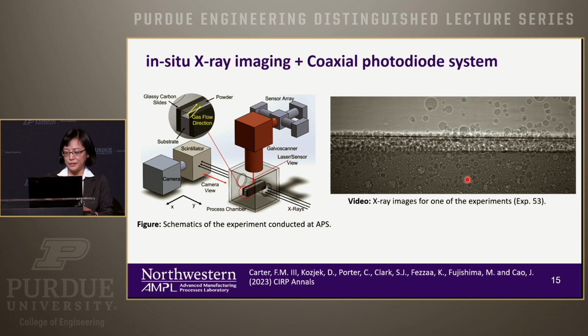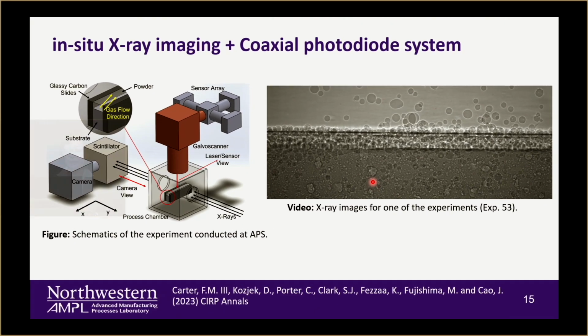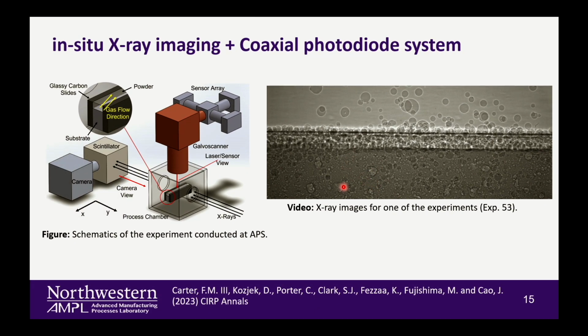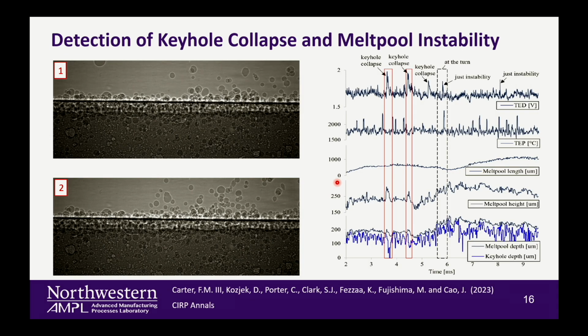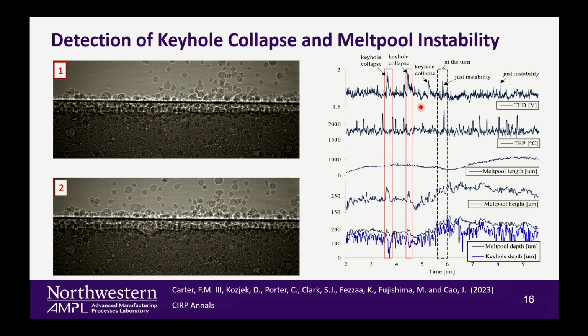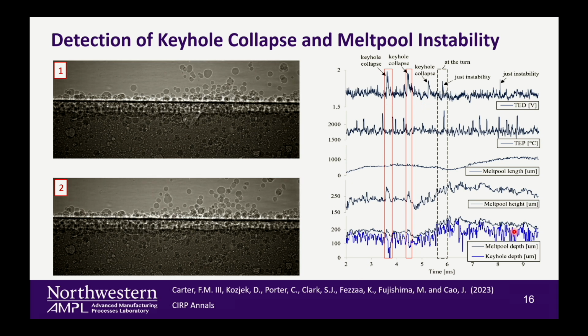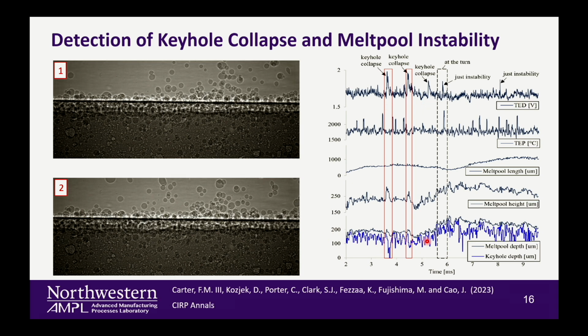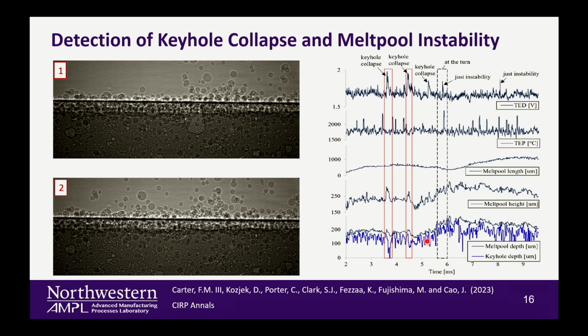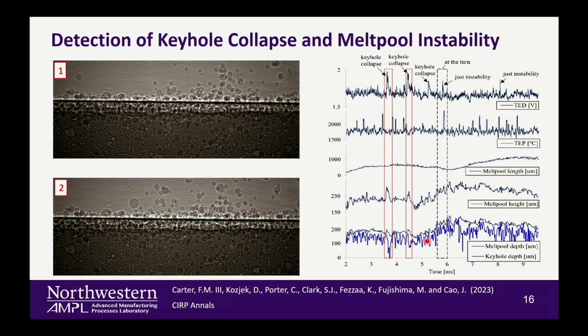This is a raw image, and after you go, you can see actually sometimes they leave keyholes. They leave a porosity right there. So it's very hard to see, right? So you process it, and the processed ones. What I want to give you attention to is the top row and the bottom row. The bottom row, particularly the blue ones. The blue ones are the melt-pool depth.